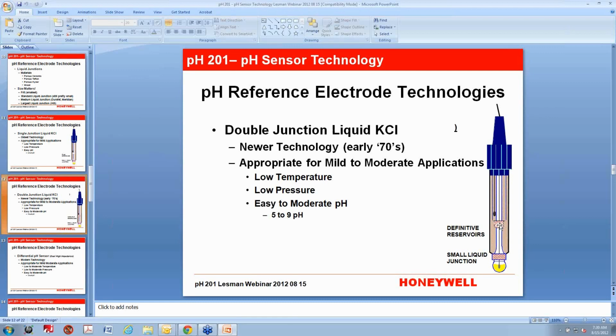And the idea is that the junctions slow down the migration of poisoning process particulates and ions into that area, because once you get process fluid around the reference electrode, the sensor stops having a stable voltage. You start seeing drift, and you have to throw the sensor away. So there are a lot of single junction and double junction sensors out on the market. This particular one is with a liquid, and I wouldn't recommend it beyond 5 to 9 pH.